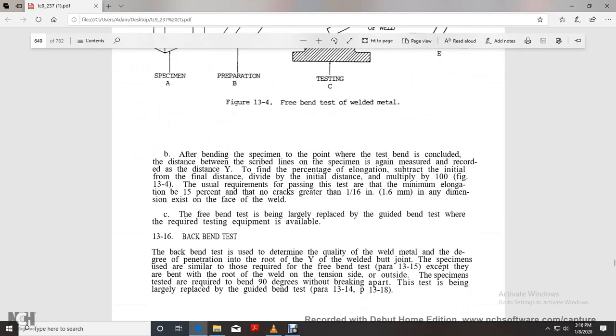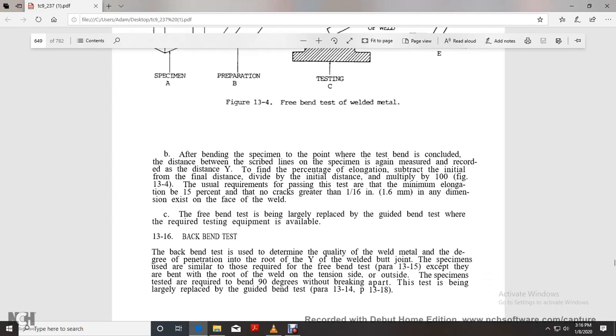After bending the specimen to the point where the test is complete, conclude by measuring the distance between the scribe lines on the specimen and recording it, to find the percent elongation: subtract the initial distance from the final distance, divide by the initial distance, and multiply by 100. The usual requirement is a minimum elongation of 15%, with no cracks greater than 1/16 inch in any dimension on the face of the weld.